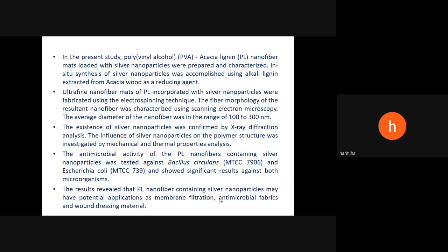These nanofibers, or the lignin polyvinyl alcohol nanofibers, were loaded with the silver nanoparticle, and we then tested them for various physicochemical properties. We found that they have the diameter in the range of 100 to 300 nanometer, and the silver nanoparticles were embedded in the structure of the fiber, and the antimicrobial activity of this fiber containing silver nanoparticle was tested against Bacillus circulans and E. coli, and they have shown significant result against them. So they can have potential application as membrane filtration, antimicrobial fabrics, wound dressing material.